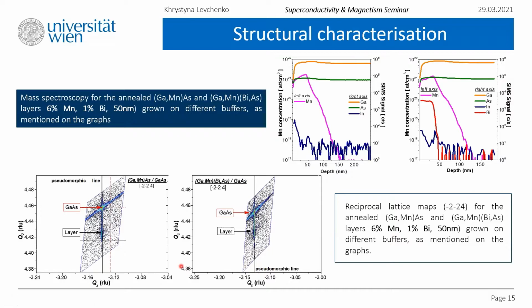High-resolution X-ray diffractometry is an important technique for characterizing the quality of the crystalline structure of the measured material. We are studying the individual Bragg peaks of the single crystals and thin films, and further analyzing sample scattering intensity as a function of outgoing direction. Why is it good? It's quick, non-destructive, highly sensitive to small changes of the lattice parameters, and allows us to study epitaxial layers a few nanometers thick.